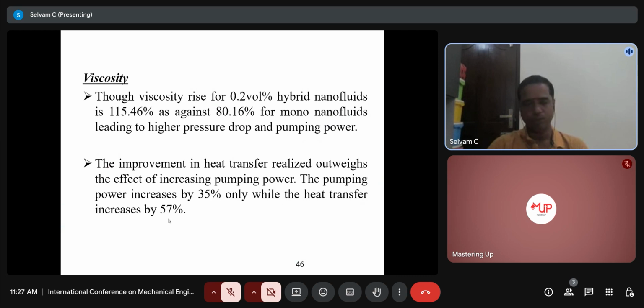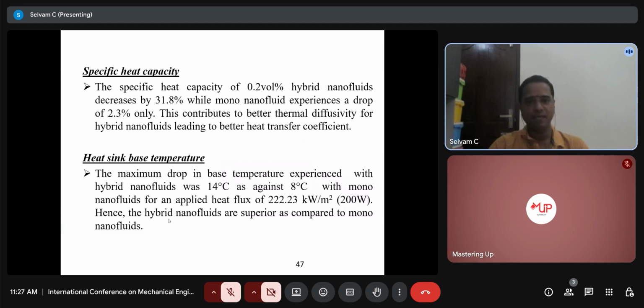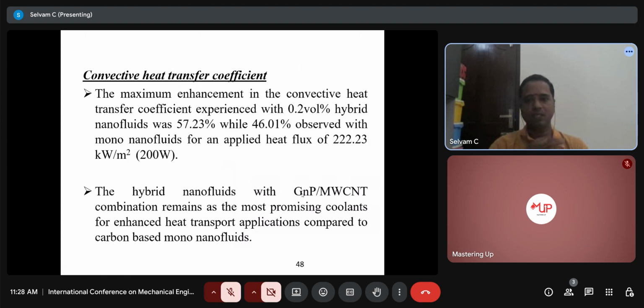And the specific heat capacity has decreased up to 31.8 percent for the hybrid nanofluid, and only 2.3 percent we have observed for the GNP nanofluid. And the base temperature decreased up to 14 degrees Celsius with the use of hybrid nanofluid, while it has been observed up to 8 degrees Celsius with the use of GNP nanofluid, or mono nanofluid. And the convective heat transfer coefficient, as I told, the hybrid nanofluid shows 57.23 percent, while it has been observed up to 46 percent for the mono nanofluid.